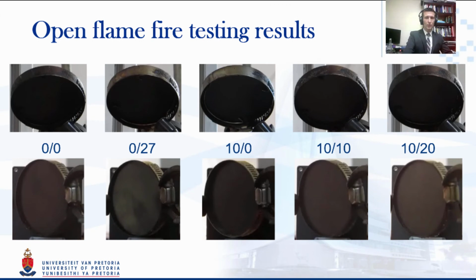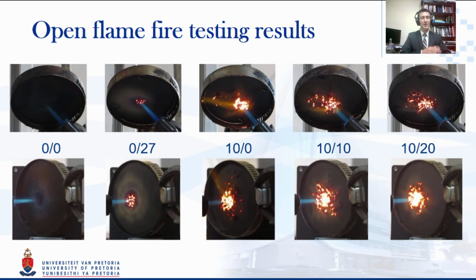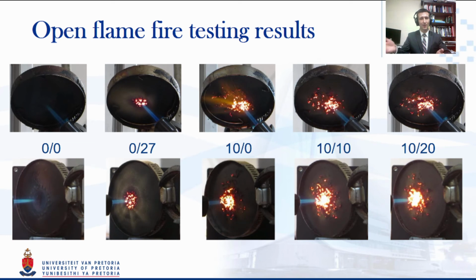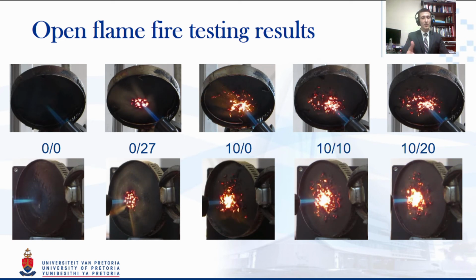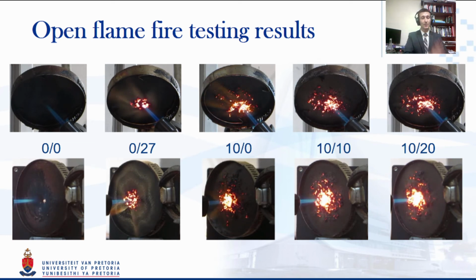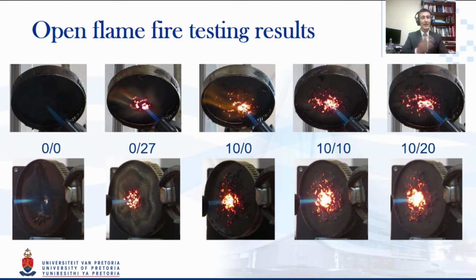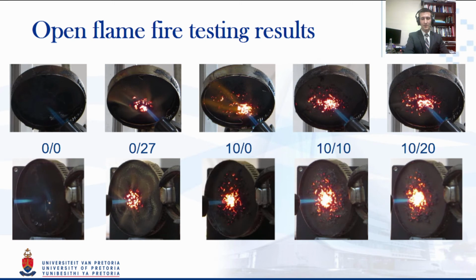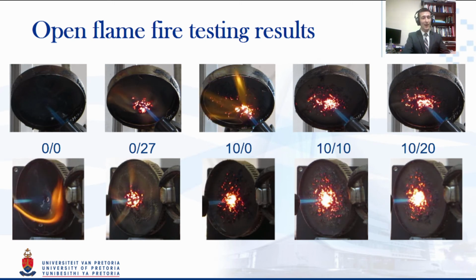So I'll go now to the video. What you'll see here is that for the open flame test, in order to develop this method, we tested at first just the low temperature expandable graphite together with each of the materials. So here you'll see on the left is the neat material, then EDAP on its own, expandable graphite, and then the combinations. And here I will indicate when their failure occurs.